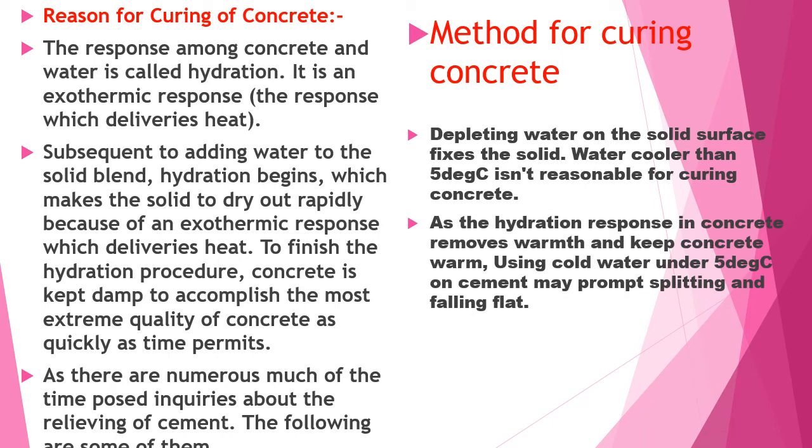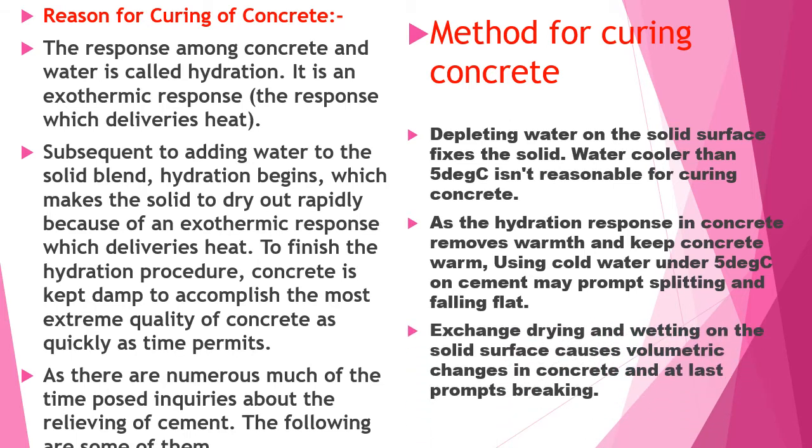As the hydration reaction in concrete gives off heat and keeps concrete warm, using cold water under 5 degrees centigrade on concrete may lead to cracking and failure. Alternate drying and wetting on the concrete surface causes volumetric changes in concrete and it ultimately leads to cracking.